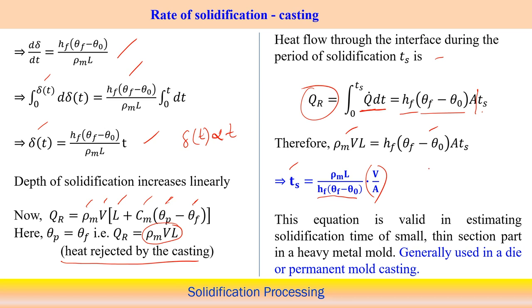Now, we can see that the solidification time is proportional to the volume by area ratio, which is different from sand casting. In sand mold casting, the solidification time is proportional to V by A square, but in die casting or permanent mold casting, the solidification time depends on the volume by area ratio. So you can clearly distinguish that, depending on which part creates more thermal resistance to the heat flow, the solidification time can vary depending upon the nature of the casting process.